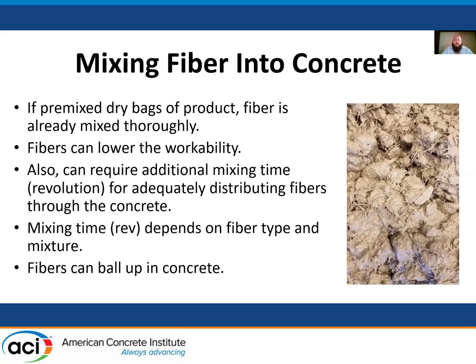impede the workability. You also have to be careful to make sure you thoroughly mix if you're going to be adding in these fibers, that you properly mix them. And so again, that may require additional mixing time. Like I said before, there's a tight window to get these fibers distributed properly. A lot of times the fiber type in the mixture, all those balance each other out. So just be aware of that.